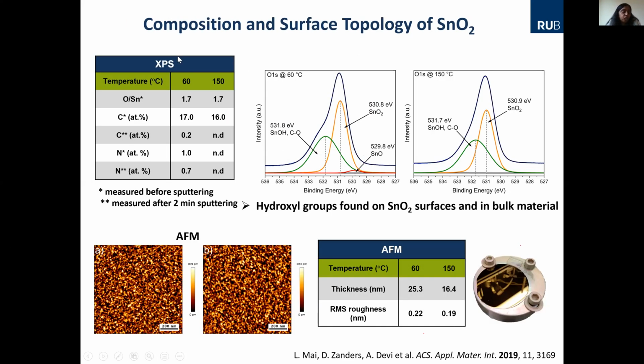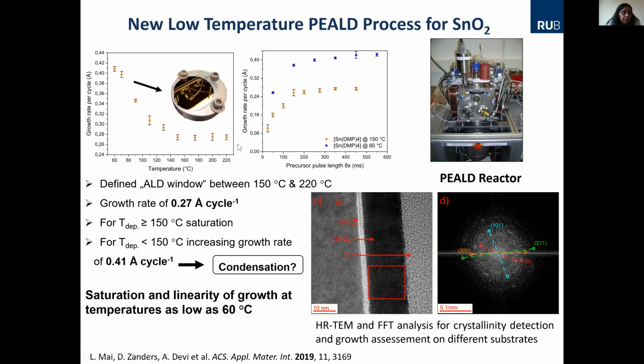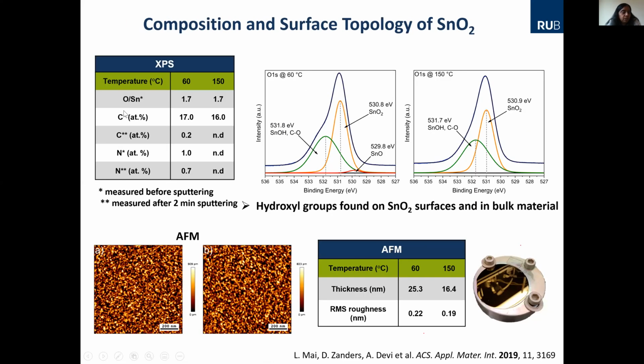So we use X-ray photoelectron spectroscopy to look into the composition at different temperatures. 60 and 150 were the two temperatures, as I showed in the slide before. Here you have 60 degrees and higher temperatures, so around 150 was optimal. And then we looked into the composition. There you can measure the X-ray photoelectron spectra, as deposited as well. As usual, when you have a film, the outer surface is contaminated with hydrocarbon from the outside atmosphere.